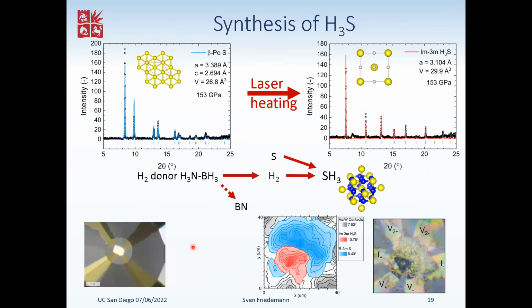So you can see that the significance is here, the intensity of the peaks. The expected pattern versus the observed pattern is very close in intensities, and that tells us that it's quite a good polycrystalline sample, meaning that the domain sizes are smallish, not too small, but we've definitely got a large ensemble of different crystallites in that polycrystalline sample.